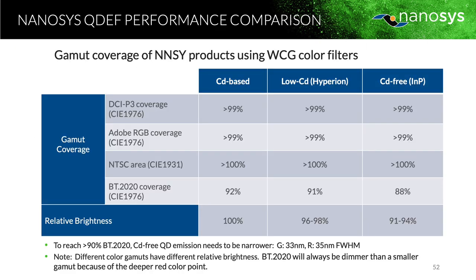So if we look at Nanosys products, we have cadmium-based, we have this Hyperion that I just talked about, and we have cad-free materials, all three of these. If we look at a variety of color gamuts, we can cover basically 100% of every color gamut except for BT2020, where you see 92, 91, and 88% for the three products, respectively. It's important to note that not only does full width half max impact brightness, as I mentioned earlier: if you have a broader full width half max, you tend to need to move the red coordinate further to where the eye is less sensitive, and that impacts display brightness. Also, as the gamut gets larger, and you have to move these out further to cover more spectral space, you lose brightness as well. So it's hard for display manufacturers to go to hypercolor gamut without sacrificing brightness, something that they don't like to do.